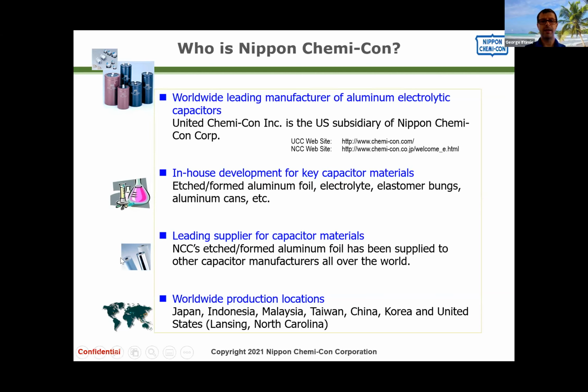We're also a big supplier of especially aluminum foil. We always supply etch foil, never formed. And the etching is basically what gives it the capacitance. The formation is what gives it the voltage rating of the part, and to a certain extent, the quality of the capacitor. We have roughly 40% of the market share for etch foil in the world. And we consume about 25% or so internally, and then we supply 15% or so to other competitors, if you want to call it that.